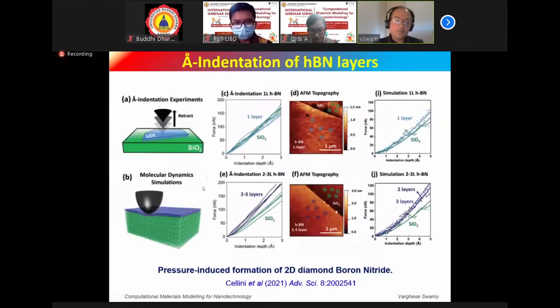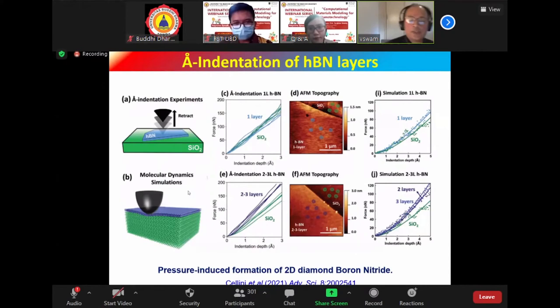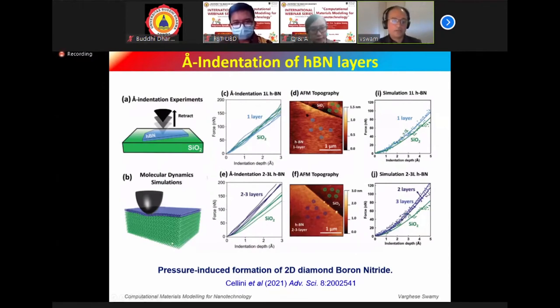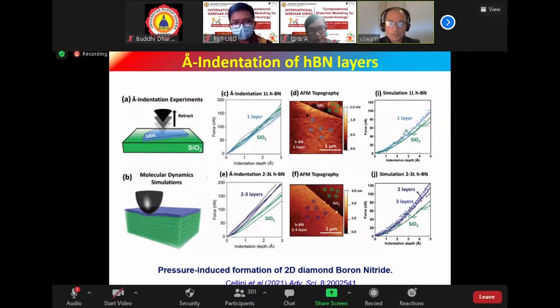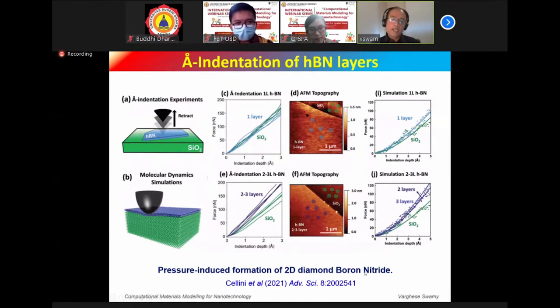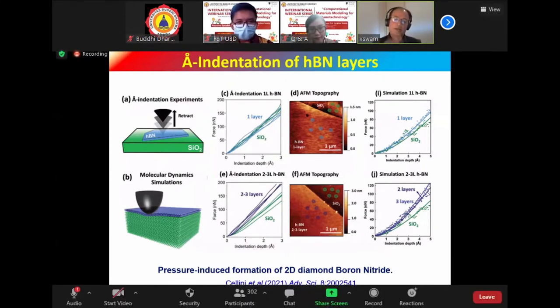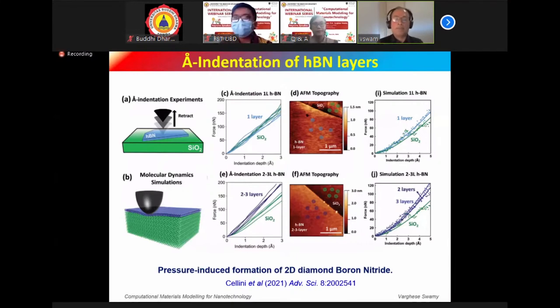Then there appears some experimental work on similar systems, on hexagonal boron nitride, where they have tried to compress hexagonal boron nitride layers, starting with one layer, two layers, up to 10 layers, to see what might happen under compression. They have done an experimental study using what's called Ångström indentation or nano indentation. It's a modified form of nano indentation. I'll show you the experimental setup in a second. And they look at what might happen to the material.